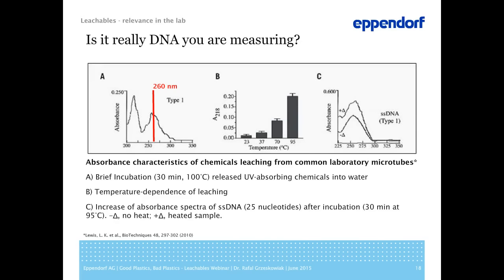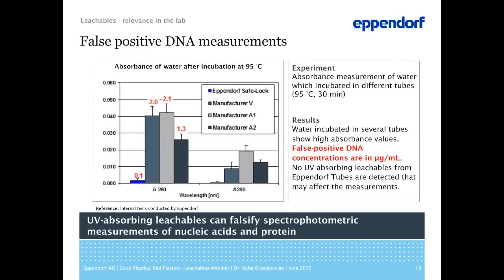And so this is a very simple assay, and from our perspective as a company developing, producing and selling consumables, we were very much interested in this effect, and these false positive DNA measurements have been investigated in more detail by our application team at Eppendorf. We found this assay to be a very quick and easy test indicative of general leachable levels and consumable quality. In our experiment shown here, we did absorbance measurements of water incubated in different tubes. The conditions were 30 minutes at 95 degrees Celsius, and we calculated theoretical DNA concentrations resulting from the absorbance at 260 nanometers. The results shown in the panel on the left side are quite striking.